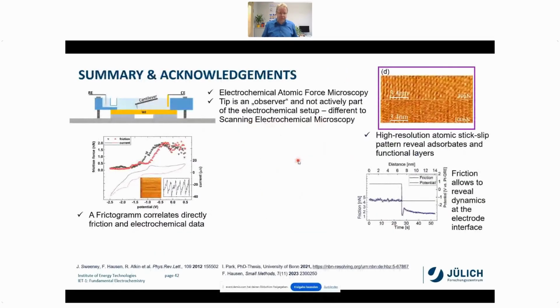With that, we come to a summary and acknowledgement. So we have shown you electrochemical atomic force microscopy. Importantly, the tip is an observer and not really actively part of the electrochemical setup. So this is different to scanning electrochemical microscopy. Ini Park has shown you the really high resolution atomic stick-slip patterns and showed you that we can differentiate between different adsorbates and functional layers at really high resolution. Which is then also helpful in ionic liquids to determine on which layer you are really measuring, and to follow the changes in electrochemistry, and that is also something where we can look at the dynamics.